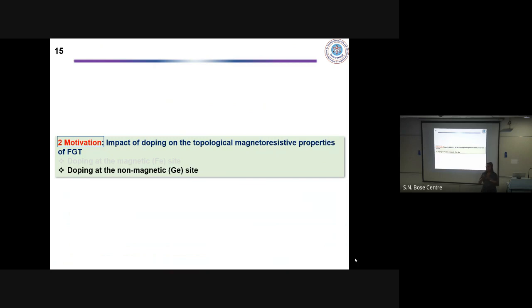that in the case of Fe3GeTe2, this kind of system, the concentration of the iron plays the key role. I have one question. This Fe3GeTe2 has three different iron sites, two? Two or three? Fe1 and Fe2, two. So this cobalt prefers which site? Do you have any idea? Theoretically it prefers the Fe2 site. However, experimentally it has been observed that it occupies randomly.